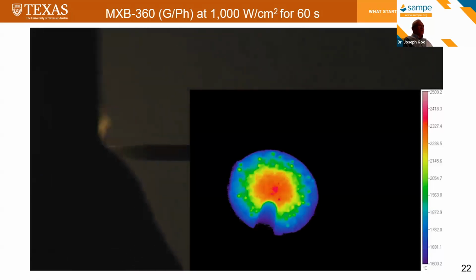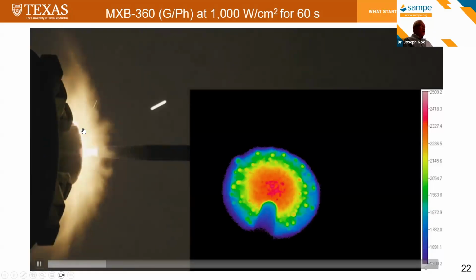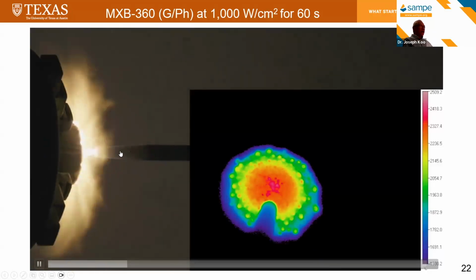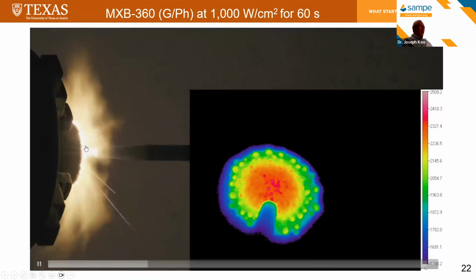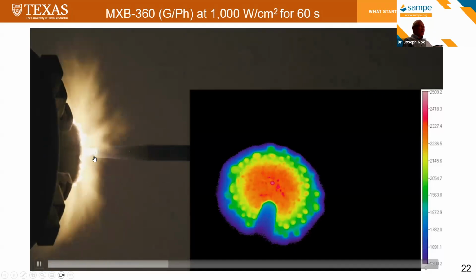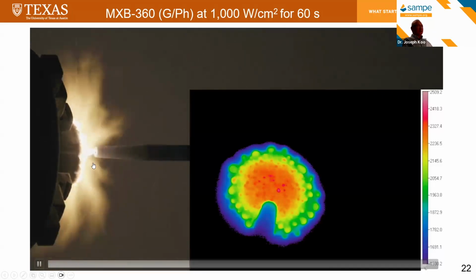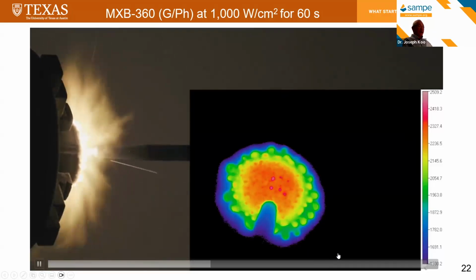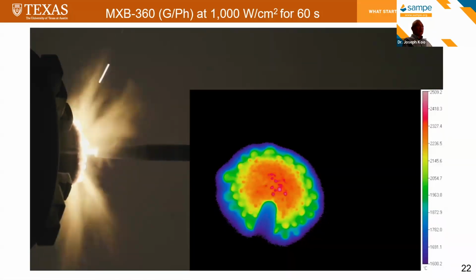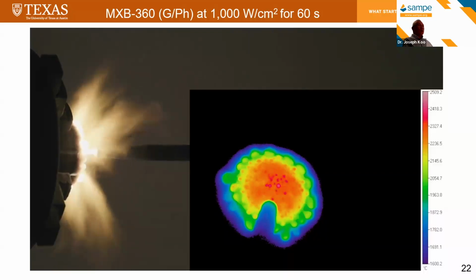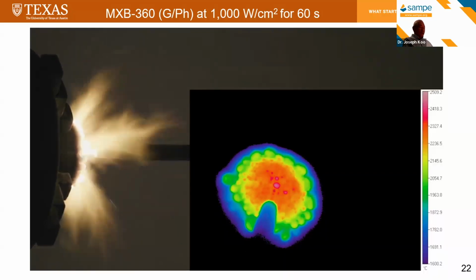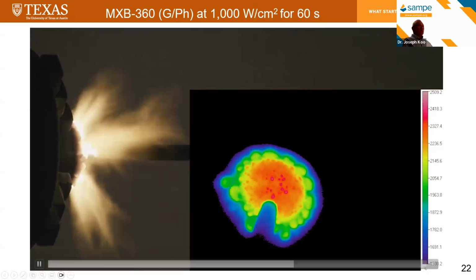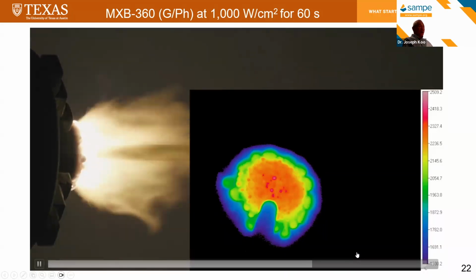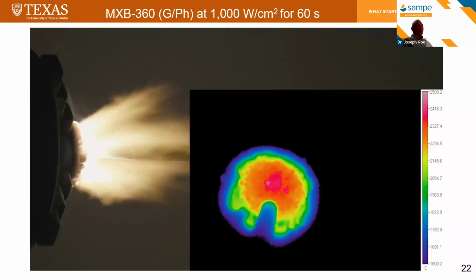All right, this is a video where we test MXB-360 carbon phenolic at a heat flux of 1,000 watts per cm squared. I'm showing you two images. On the left-hand side, you can see how the material responds at this heat flux, and on the right-hand side, we have a thermal map of the material during the testing. These are all the data we collected during the testing. That's how we are able to understand the morphology, the behavior, and the surface, and understand why these materials are working well.